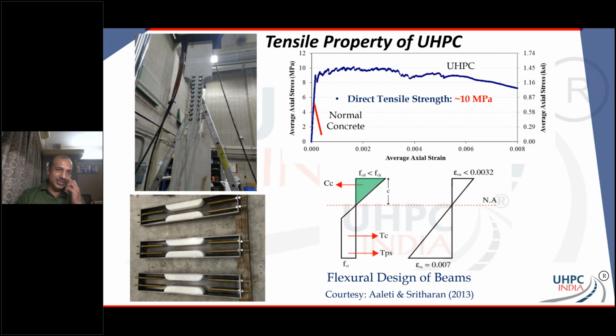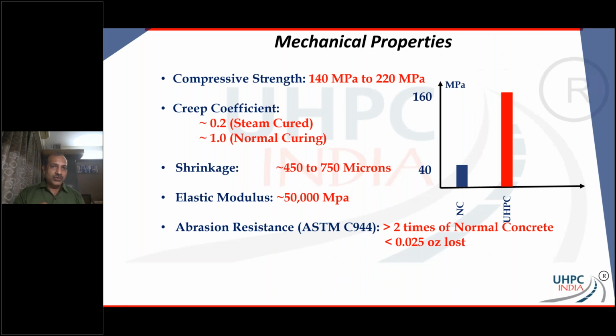On the left side, these are some pictures of direct tension tests that I was involved with at Iowa State University. These direct tension tests give you a good measure of the tensile strength. So these are not the flexural capacities or flexural strength, but the direct tensile strength. It also tells you how far you're going to go with your ductility or your strain. So UHPC exhibits very high mechanical and durability properties.